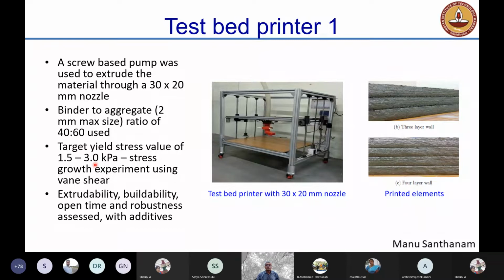Okay, now you need a rheometer to do the rheological measurements, but we went to the conventional techniques like a vane shear that is typically used in geotechnical engineering to establish the shear stress or yield shear stress of this material. And we use that as the basis for our mix design process. We did several studies to ensure that the mixes that we created were extrudable, right? That means they could be pushed out of the nozzle. Buildable, that means they could be put layer upon layer. They had significant open time. Open time means how long can you work with the concrete?